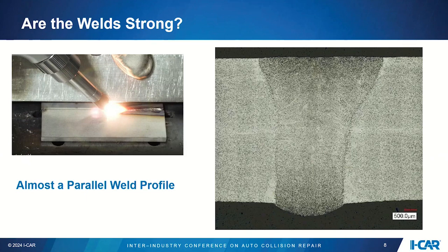So this is the other thing too, when you take a MIG or a TIG weld and you dissect that weld, you cut it in half, you look at the profile. What you see normally is a tornado, a conical shape. Yes. And this is an example, I think this is 1/8 inch material, where the weld, even though it's not parallel, is a lot more parallel than you would think.